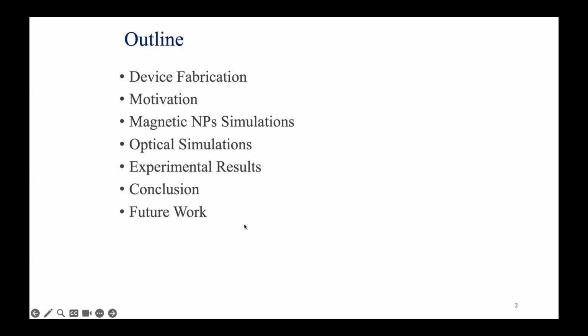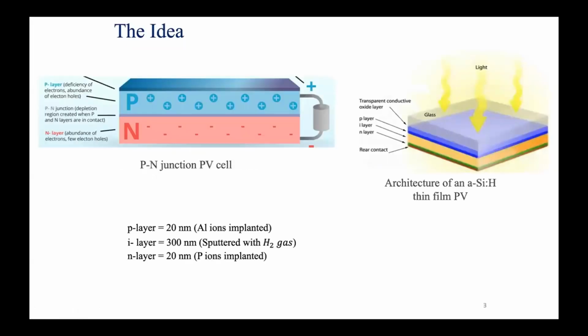Firstly, there are two ideas that we were planning to fabricate. The first one was a PN junction and a PIN junction, and these are the layers that we're supposed to fabricate. The P layer was supposed to be 20 nanometers, made P type by embedding aluminum ions, and the intrinsic layer was supposed to be 300 nanometers, and the N layer is 20 nanometers.